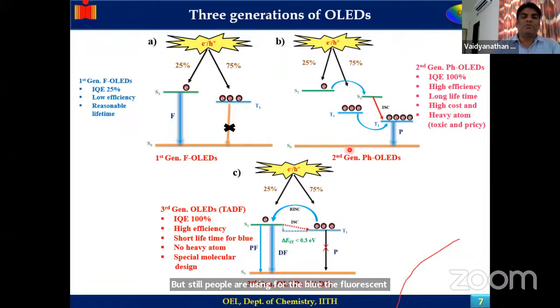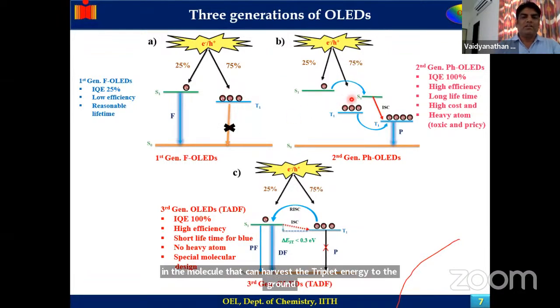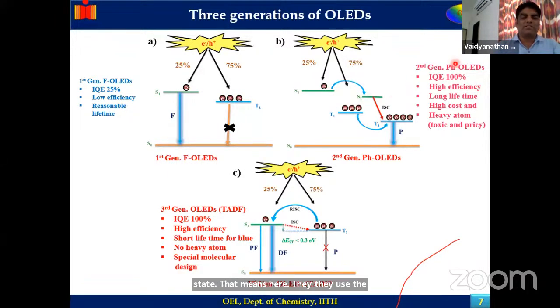Twenty years back, in the 2000s, the second generation OLED was discovered. As I already told you, a heavy metal ion, if present in the molecule, can harvest the triplet energy to the ground state. That means here they use platinum or ruthenium complexes, platinum or iridium complexes, to harvest this energy to the ground state. That means one can get the internal quantum efficiency up to 100%. It shows high efficiency and long lifetime, but also high cost, and the heavy metal ion present can be toxic and pricey in nature, which restricted the use of the second generation OLED in a commercial manner.